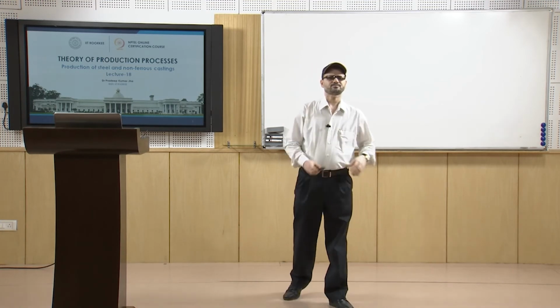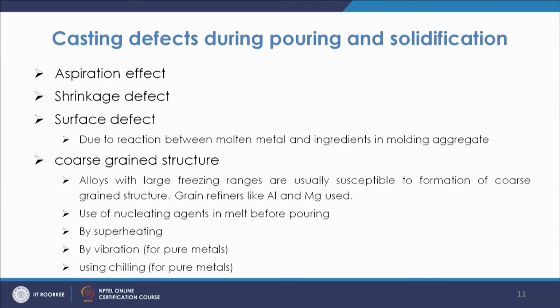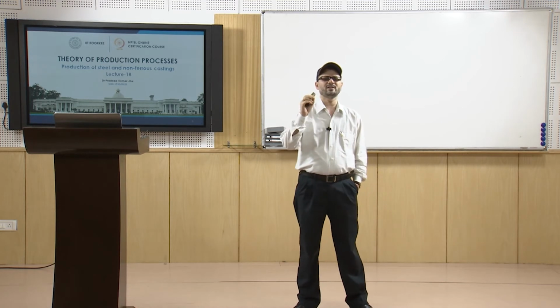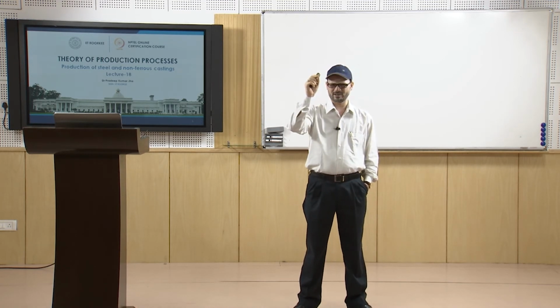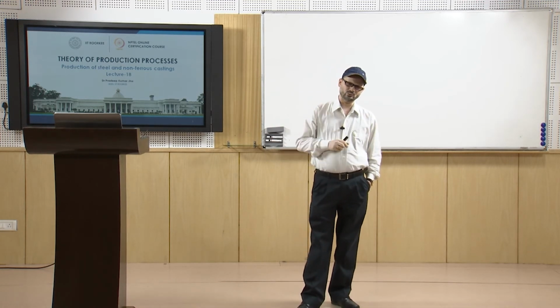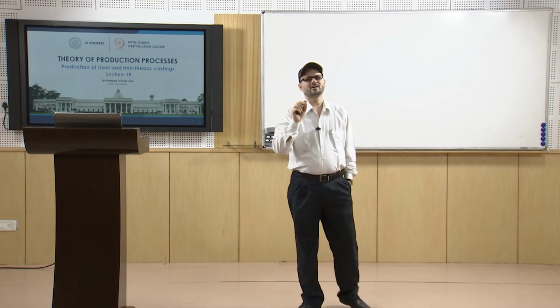Then you have the coarse grained structure also, like if you have the large freezing range alloys. So, they are usually susceptible to formation of coarse grained structure. So, in that case during the solidification itself, you will have the growth of the grains in such a manner that you have the large grain structures in those cases, and many a times you use the nucleating agents in the melt before pouring. So, in the case of non-ferrous material, this is very much common practice that we use the alloying elements, and many a times many of the alloying elements, its main purpose is to act as the nucleating agent, or they try to basically make the grains finer.